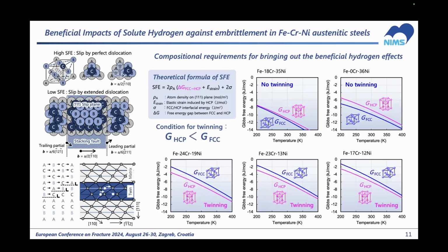As some of you here know, the deformation twinning in FCC metals generally originates from the overlapping of stacking faults, which are bounded by two Shockley partial dislocations. And inside of such a stacking fault, we can find some local HCP crystal structures. So the stacking fault energy is a direct function of the energetic relationship between FCC and HCP. If we calculate the energetic relationship, we can estimate the requirement for the onset of deformation twinning.